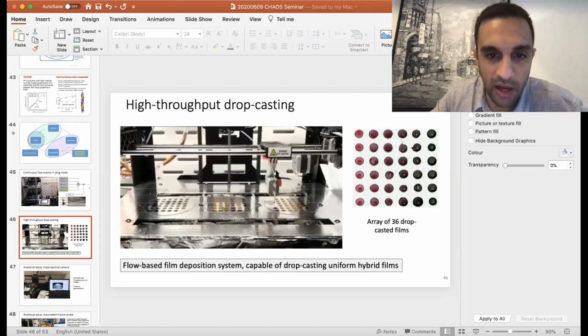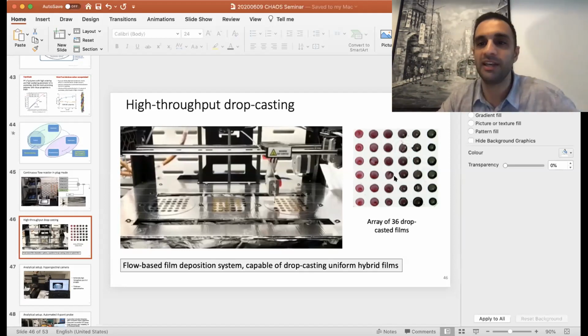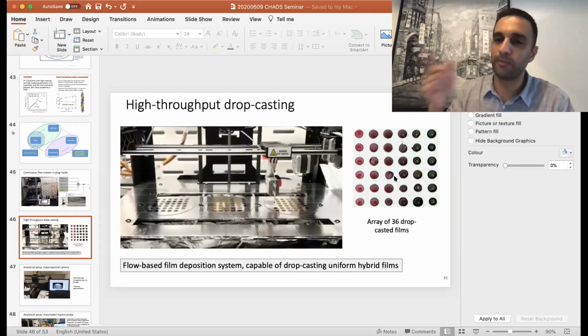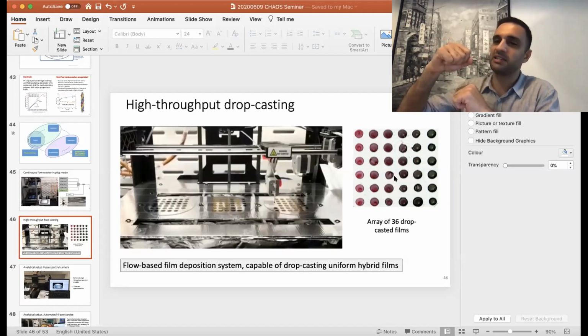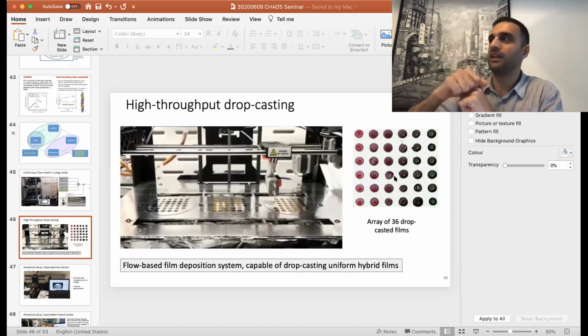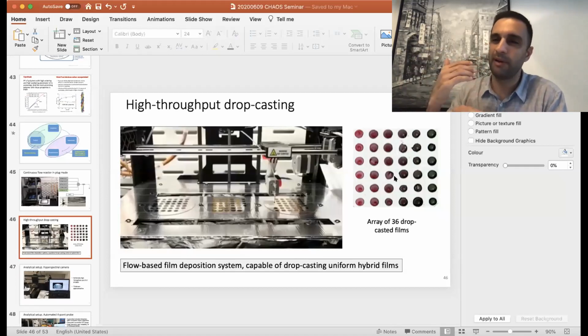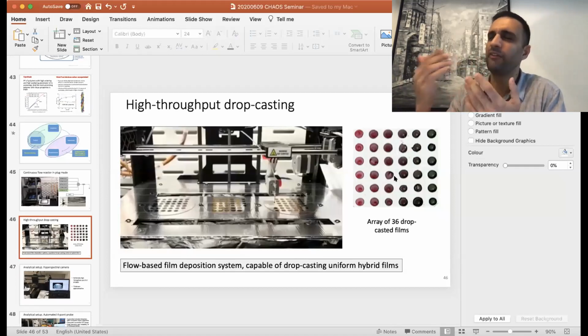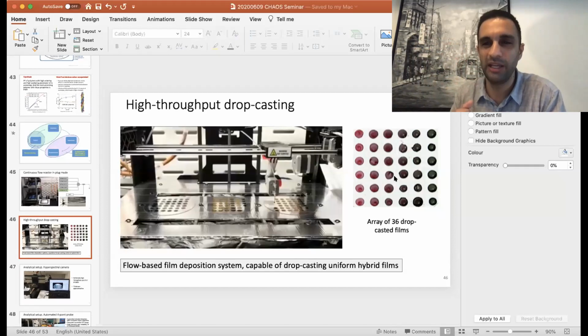Deepa S. Narang asks, is it possible to make 2D layered materials from non-layered materials? That is a difficult question. You can make 3D materials from 2D layered materials, but vice versa is difficult, because the chemical bonding along the C-axis can be quite strong. You have to do it through some chemical means, perhaps. You can do layer by layer etching, but it's very difficult to get selective etching layer by layer. So you can probably do it, but you'll damage the subsequent layers underneath as well. So it's not an easy challenge, I would think.